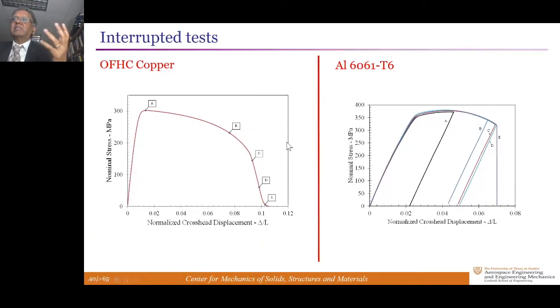We do tension tests. Everybody does this to characterize material properties. But we did what are called interrupted tests. These were commonly used, but not so in recent years. The idea of an interrupted test is you run the test once all the way until failure, so you know what the global response looks like for both materials. Then you run it to the peak load, unload it, put away that specimen. Run to another load level, third, fourth, fifth, progressively approaching failure, and unload them and examine the specimens that have been unloaded. The idea is this is again an evolutionary process. Something is going on. Both deformation and failure mechanisms start at some point and progress as you continue the loading. A trail of what happened there is left in the unloaded specimens. If you can interrogate them and explore them in great detail, you will learn something about what happens.